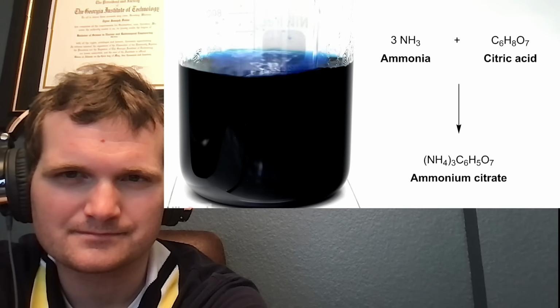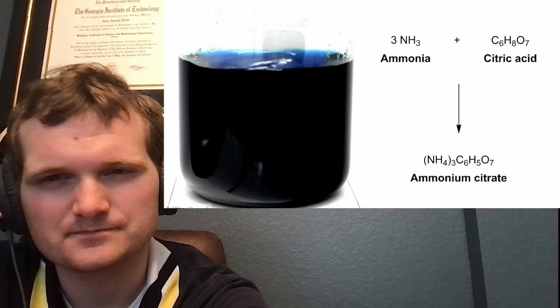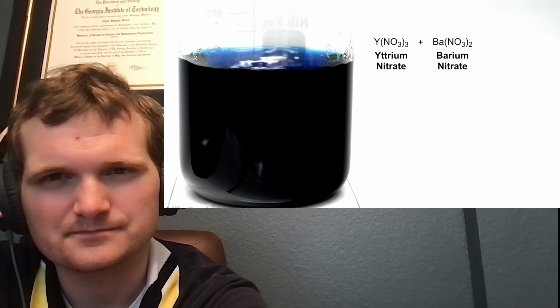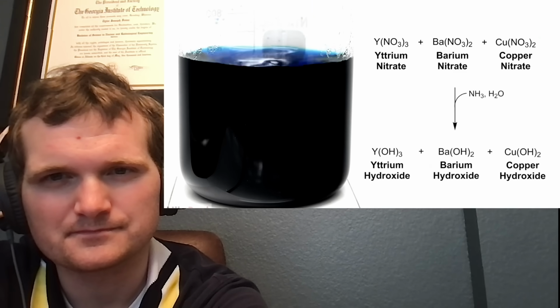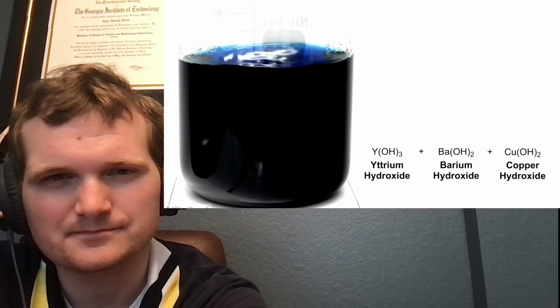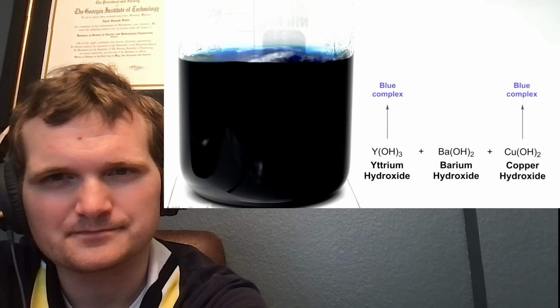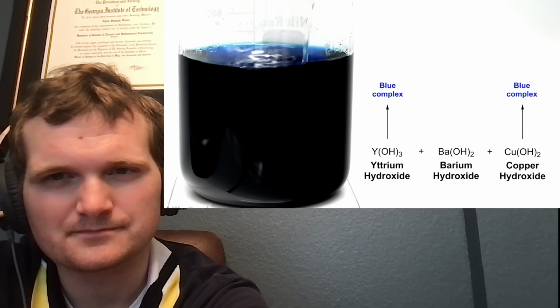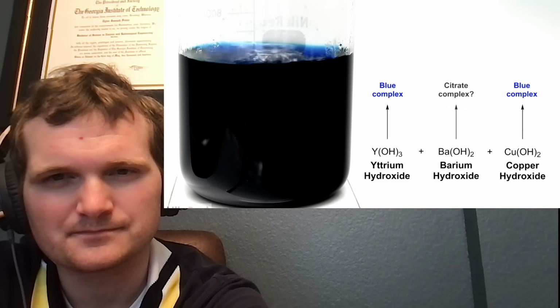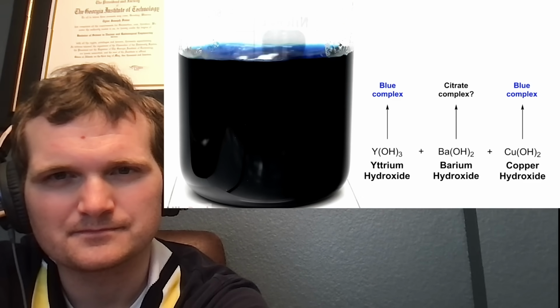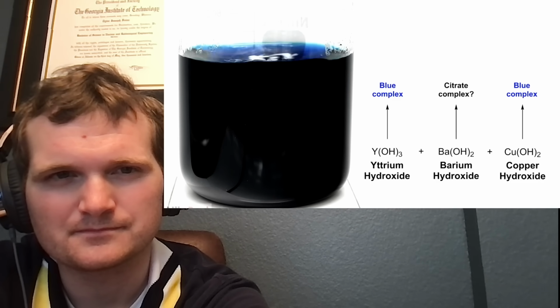The first major reaction that was happening here was between the basic ammonia and the citric acid, and it was turning it all into ammonium citrate. It was also reacting, though, with the yttrium, barium, and copper nitrate, and turning them into hydroxides. The copper and yttrium hydroxides then reacted with more ammonia to form dark blue complexes. I don't think the barium was complexing with the ammonia, though, and it was instead forming a complex with the ammonium citrate. However, I really don't know that for sure, and I had a very hard time finding any decent info about this reaction in general.